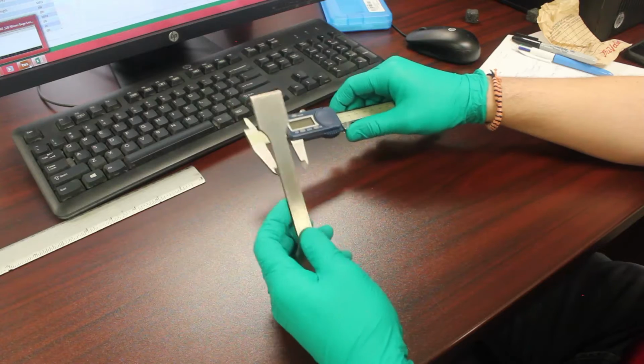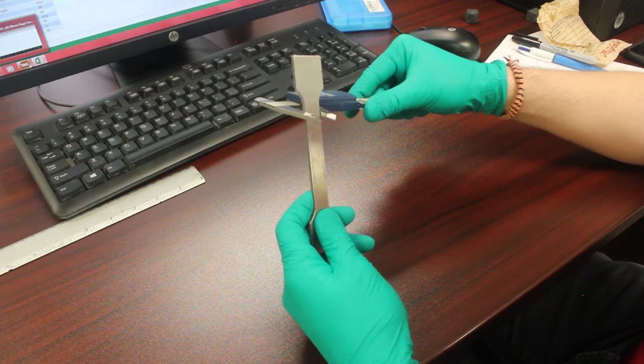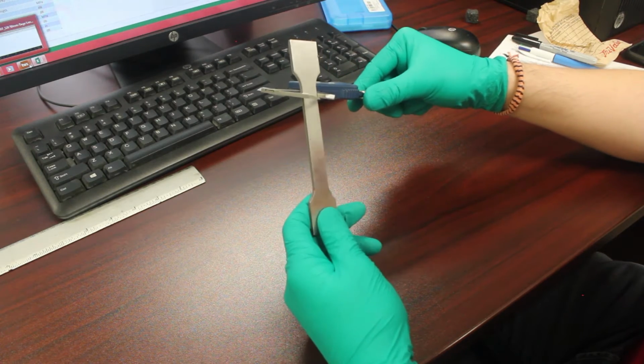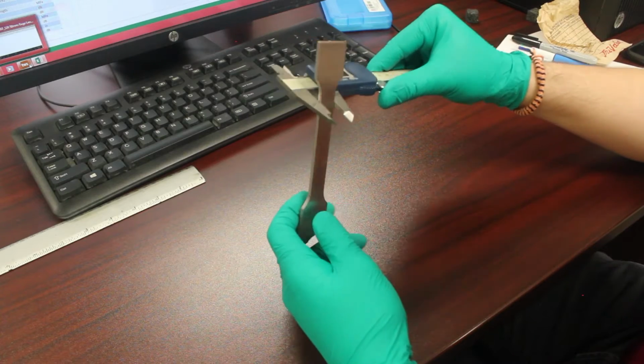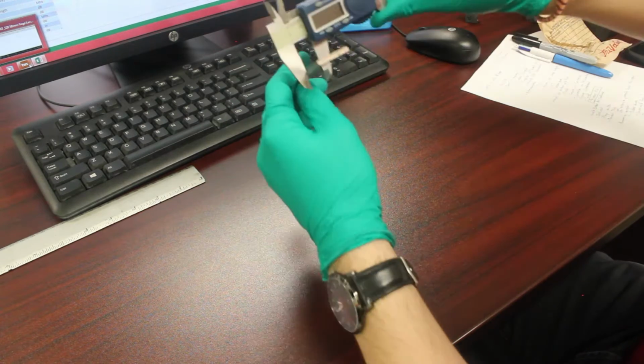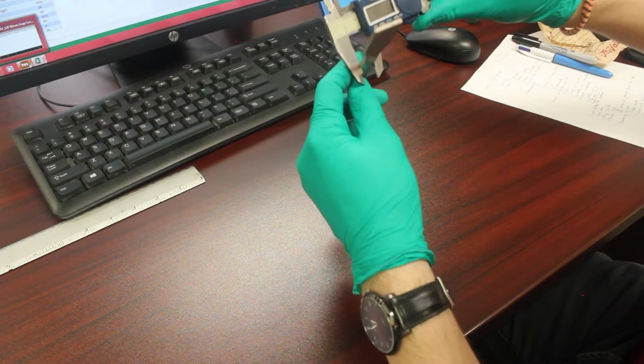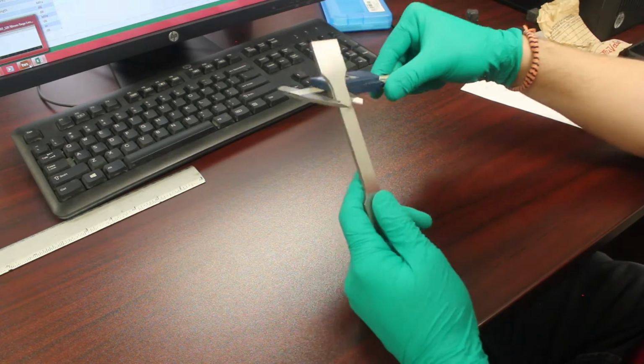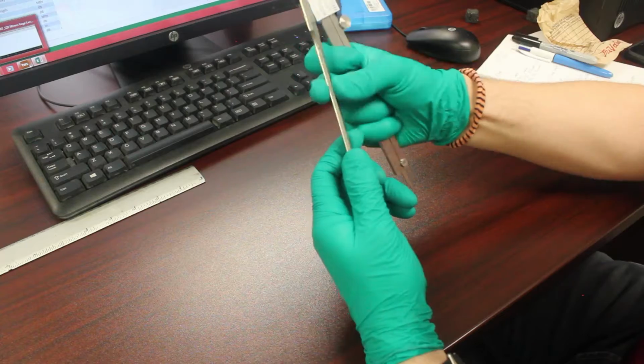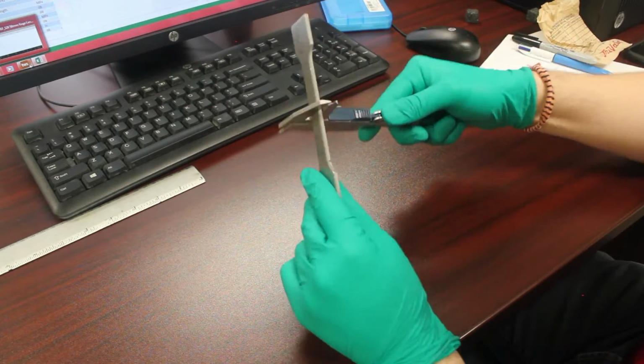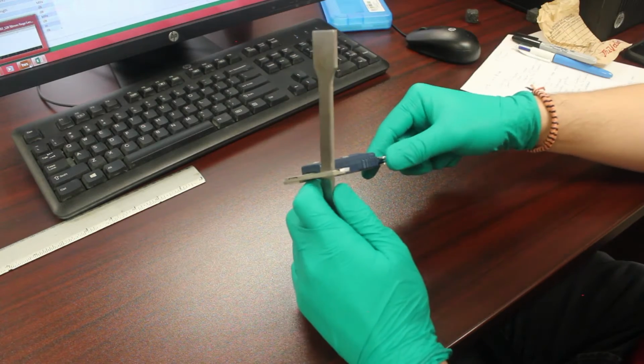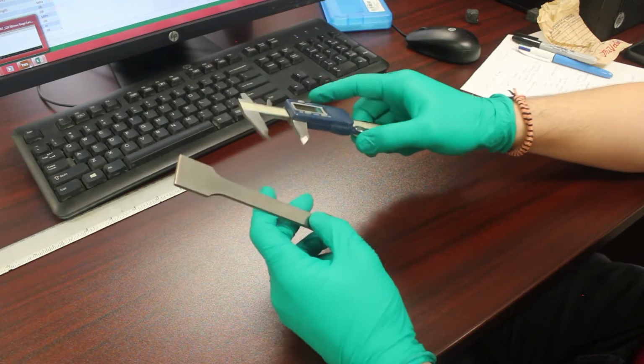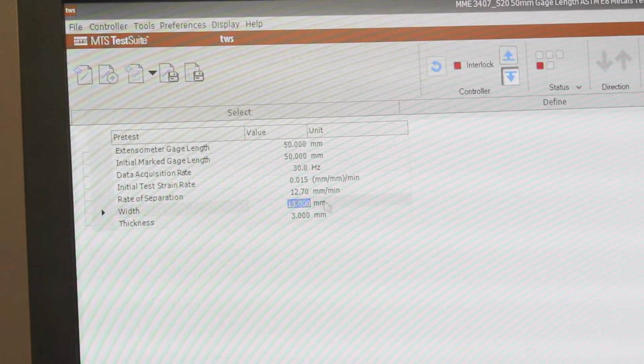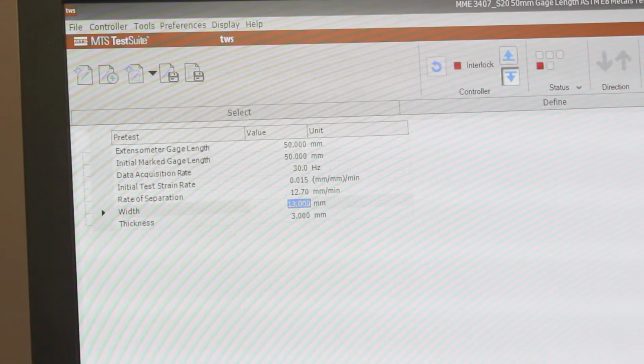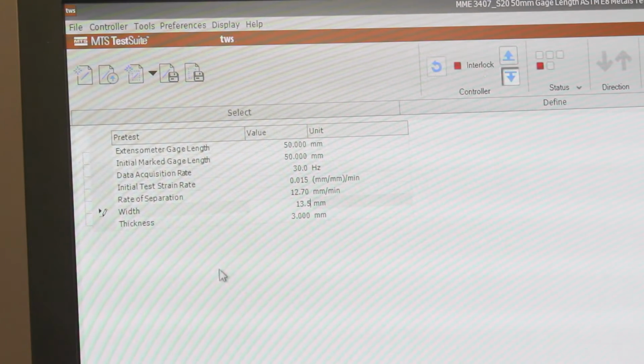Next, you're going to measure your sample for the initial dimensions before the test. First, you're going to measure the width. Make sure to take a measurement from the top, middle, and bottom of the gauge length to get an average reading. Turn it sideways, do the same thing for the thickness, and record your results. Take your results and input the average width and the average thickness into the test parameters page.